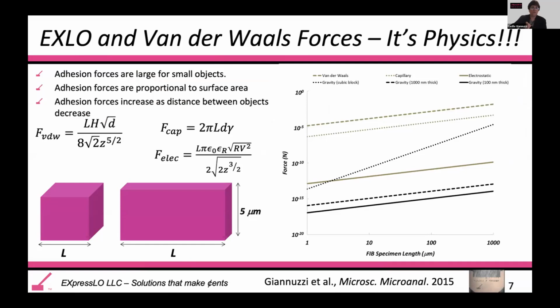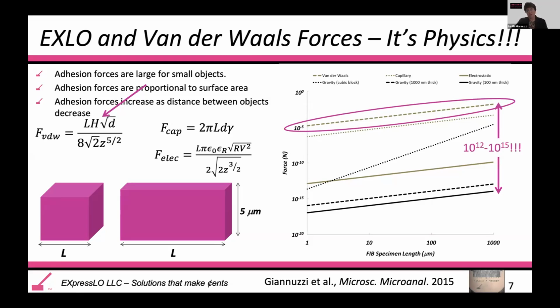The reason is, if you take a look at adhesion forces at very small scales, you find that adhesion forces are proportional to surface area. Early on, we thought that the ex situ lift out technique was primarily due to electrostatic forces. But if you take a look at these adhesion forces, you see that the large contribution is actually due to the van der Waals forces. If you plot a log scale of force versus FIB specimen length, you can see this very large 10 to the 12 to 10 to the 15 orders of magnitude force over, for example, the force of gravity.